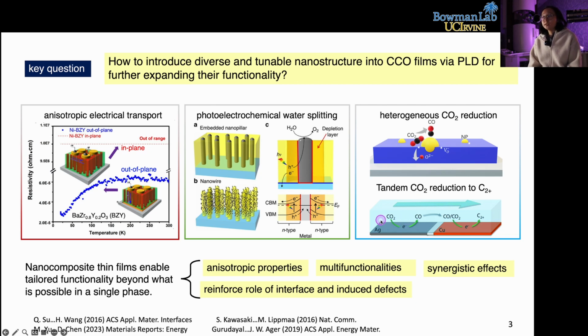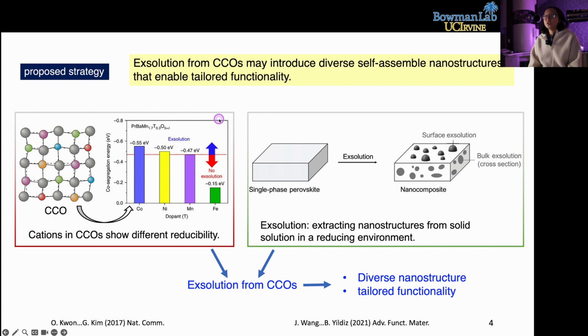But the research question is how to introduce diverse and controllable nanostructures into the CCO films post-deposition, expanding their functionality. To solve this problem, my strategy is to use exsolution to introduce a self-assembled nanostructure. Exsolution is a process that can extract nanostructures from a solid solution in a reducing environment. In the CCO, we know there are multiple cations, and each cation shows different reducibility. If we can control the exsolution extent or exsolution condition, and also tune the CCO's composition, we can introduce diverse nanostructures with controllable size and morphology to maximize the functionality of CCOs.